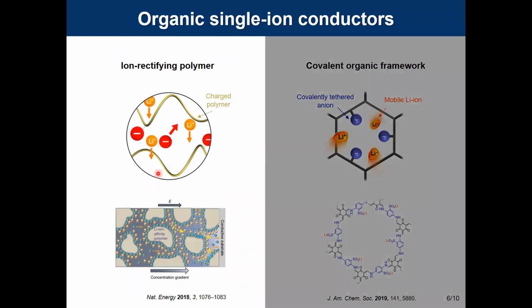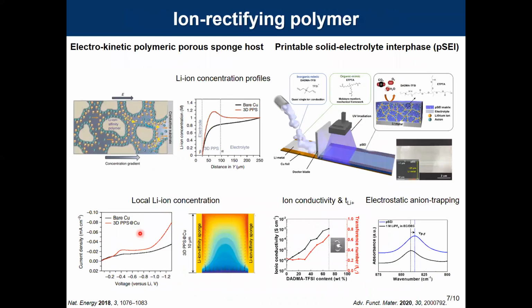Firstly, let's focus on ion-rectifying polymers that allow facile lithium-ion transport. In this part, I'd like to say something about a polymeric porous sponge host that can lead to higher local concentration of lithium ions than the bulk solution. So the interfacial electric double layer, due to the strong lithium ion affinity, promotes electrokinetic surface conduction and electroosmosis. In other words, the electrokinetic pumping feature could accelerate the lithium ion transport in the host and therefore improve the lithium ion self-concentrating kinetics.